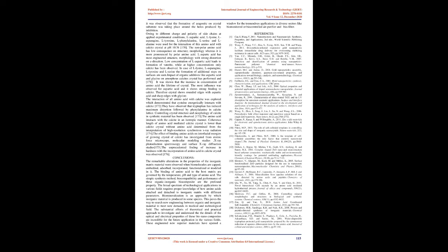The formation of histidine-capped ZnO has been systematically explained by considering the ratio of Zn2+ to OH and Zn2+ to histidine molecule. They have observed that histidine or OH are binding to Zn2+ at different constant values, and therefore Zn, O, N and Zn, C6H9N3O2, N complexes are formed. A variety of morphologies like prism, flower, and crystalline hollow microsphere were formed with L-histidine by varying the ratio of zinc ion and hydroxide ion.